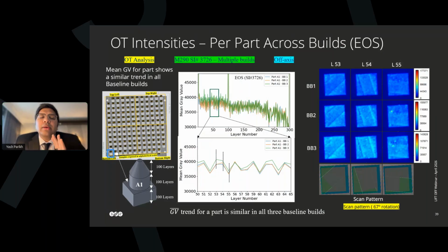So what I'm trying to tell you from this slide is I investigated A1. Why did I choose A1 for the first one? Because that is the region of a sample which had two different OT variations between the EOS and OSU sample. And you'll see in a second, I looked at A1 and I said, give me the whole first 50 to 65 layers of information on OT for three build jobs, or three A1s that we printed. And the signature of A1 tells me a different story.